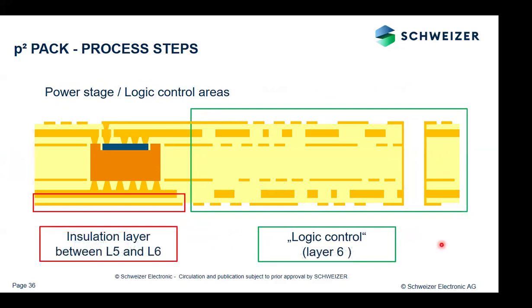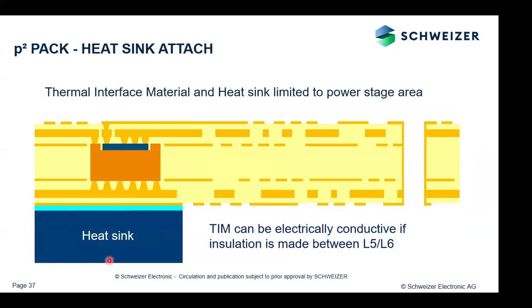What you can now add is also an insulating layer underneath the power stage to have the insulation already built into the PCB. Because for high voltage, this is very interesting for our customers, because you achieve very low thermal resistances. And after doing that, you can also apply a heat sink with a thermal interface material directly under your power stage. And because there is already an insulation present in the buildup of the PCB, this thermal interface material can now be electrically conductive.